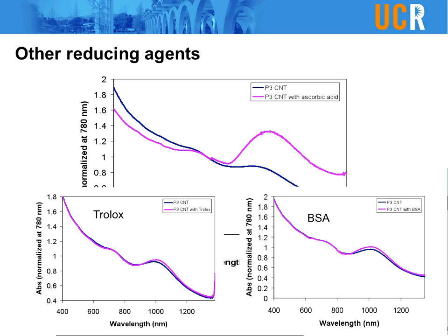We also take the absorption spectrum of Trolox, which can indicate its oxidation, because upon oxidation, the maximum absorption of the Trolox will change from 290 to 275. So from that spectrum, we can judge if Trolox is being oxidized or not. But by the CNT itself, Trolox would not be oxidized, at least not to the level that we can observe using the spectroscopy method.